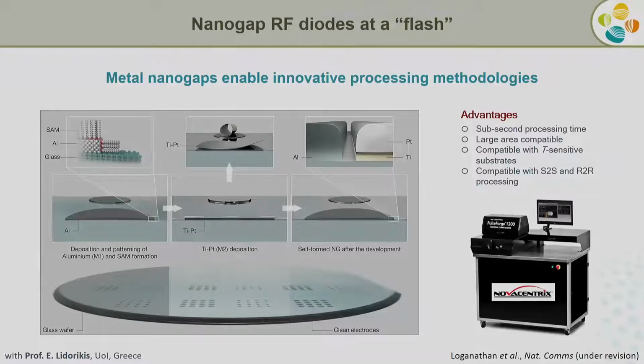And what we discover is that the metal absorbs part of this light and heats up momentarily, just for a few milliseconds. But the heating can reach temperatures up to 500-600 degrees Celsius, which, when we put them very close together, will start coupling temperature from one side of the two electrodes to the other and converting the precursor material in there to the stable phase, which is the semiconducting phase. So essentially, you're performing chemistry within a few milliseconds, but using very little energy. And you can do that on inexpensive substrate technology. You don't need to have silicon or glass. It can be done on plastic or paper. So it enables us to use low energy technologies to produce something quite sophisticated.